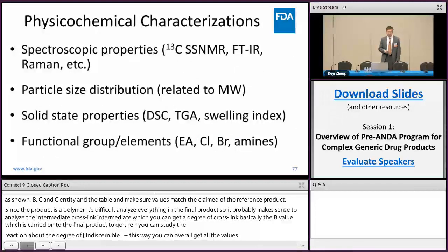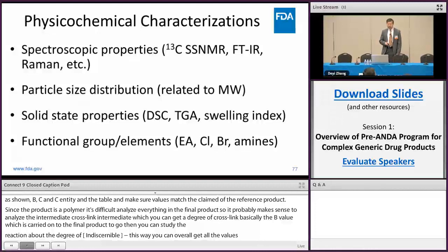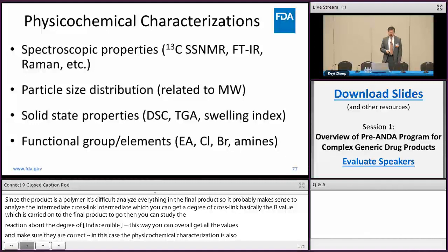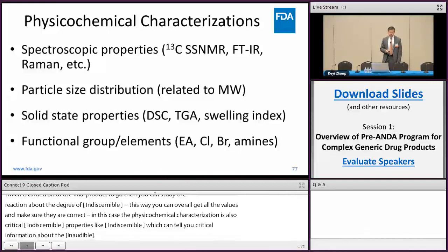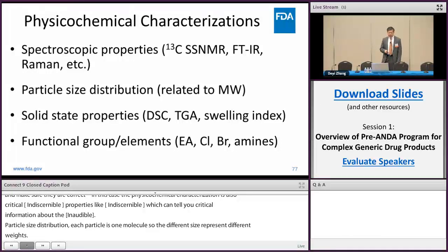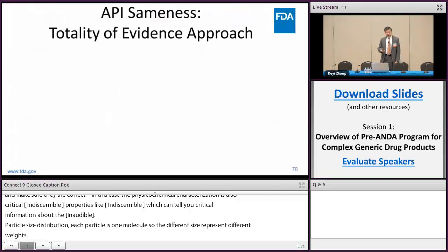Physical-chemical characterization is also critical for colesevelam. For example, spectroscopic approaches like solid-state Carbon-13 NMR can provide critical information about the cross-linked structure. Particle size distribution is important because each particle is essentially one molecule, so different particle sizes represent different molecular weights. Thermal methods such as DSC and TGA, as well as swelling index — which directly correlates to the degree of cross-linking — are also important. Functional group analysis and elemental analysis round out the characterization. Once you demonstrate equivalence in all those aspects, you can say you used a totality of evidence approach to demonstrate API sameness.